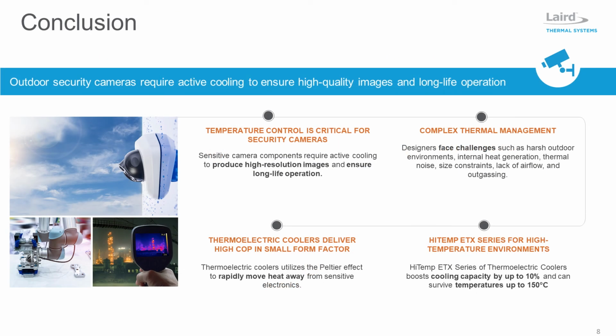Imaging sensors and other sensitive camera components require active cooling to keep operating temperatures below their maximum limit, ensuring high-quality images and long-life operation. Designers are also tasked with challenges such as thermal noise, size constraints, lack of airflow, and outgassing. By utilizing the Peltier effect, thermoelectric coolers create a temperature differential across the module and rapidly move heat away from sensitive electronics. The enhanced HiTemp ETX series thermoelectric cooler offers a high COP, boosts cooling capacity by up to 10%, and is tested to withstand temperatures up to 150 degrees C, exceeding most outdoor applications.